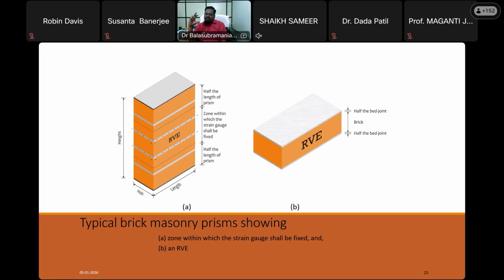So the gauge length has to be decided based on the height of the representative volume element, and it should be in multiples. Unlike mortar, here the representative volume element size and the specimen size are not very different. In the case of mortar, the sand particle sizes are much smaller compared to the volume of the specimen, isn't it? But in the case of masonry, the volume of the representative element is significant. Because of that, we are restricting this criteria: the height of the gauge length should be in terms of multiples of representative volume elements.